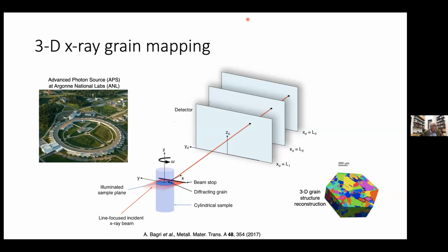Yeah, multigrain diffraction is also a growing area for in situ high pressure, and that's being done at HPCAT. Another sort of validation point concerns when you calculate an interfacial energy, for example, to what extent can you validate those kinds of predictions, say with calorimetry? Can you extract that information calorimetrically? Not that I'm aware of, not through calorimetry, at least not conventional calorimetry.